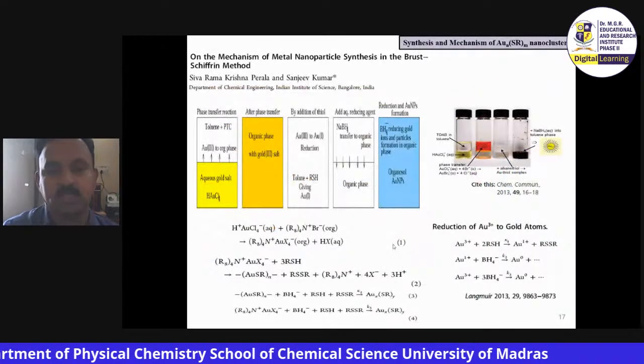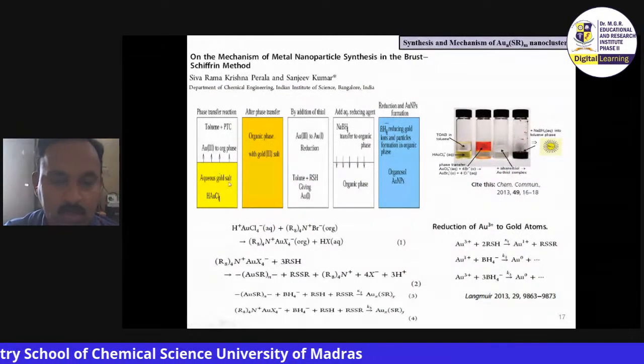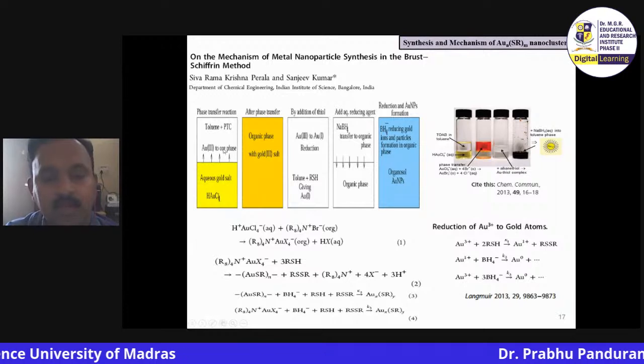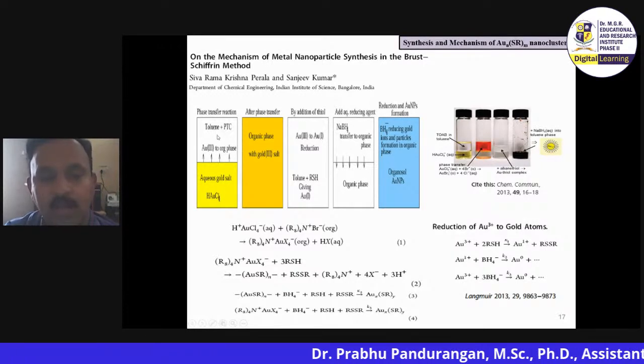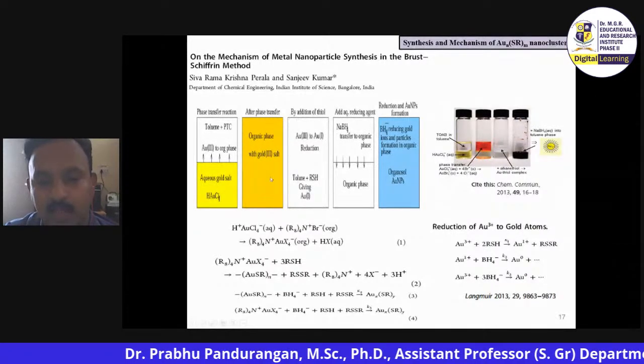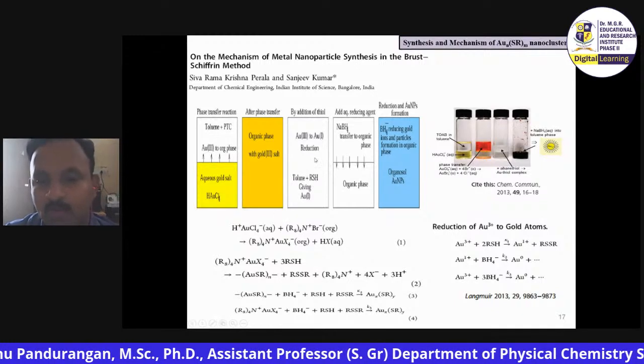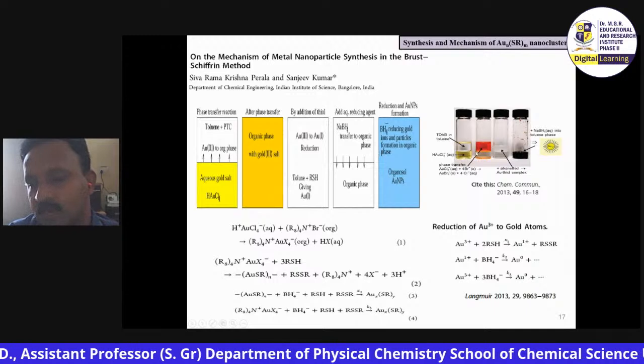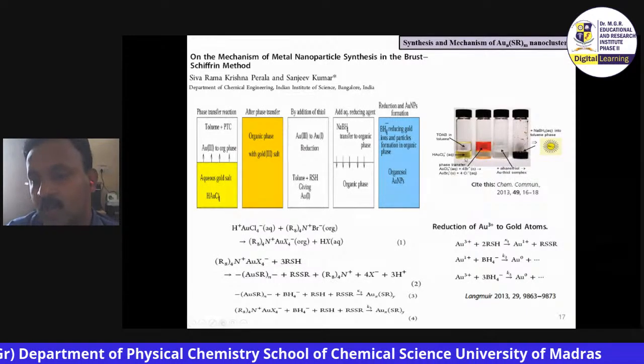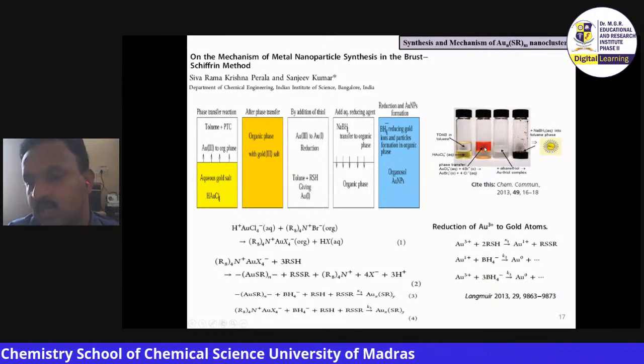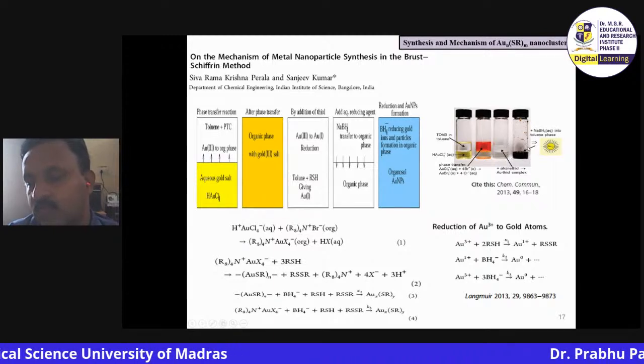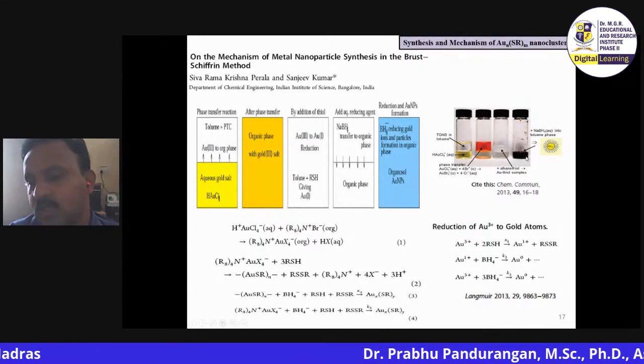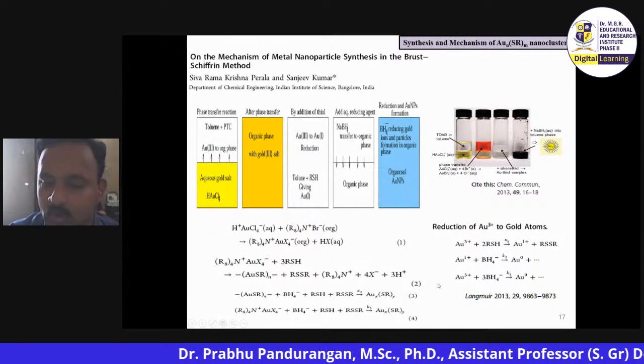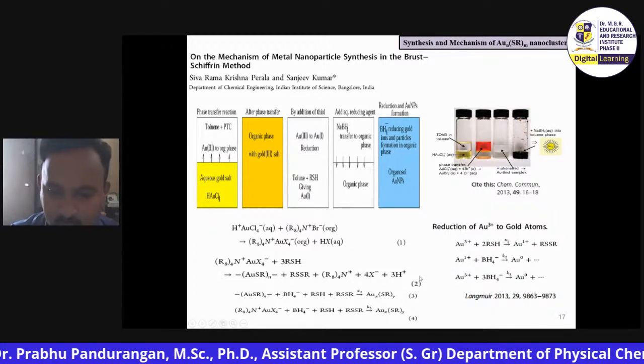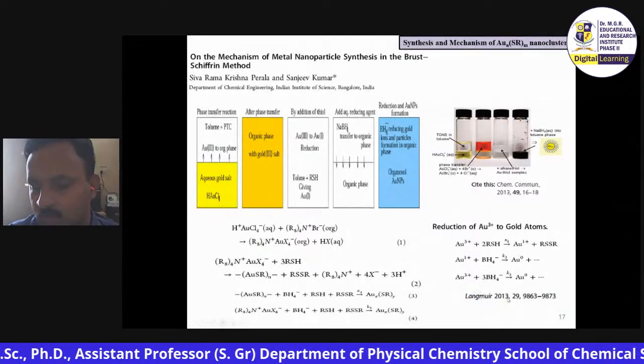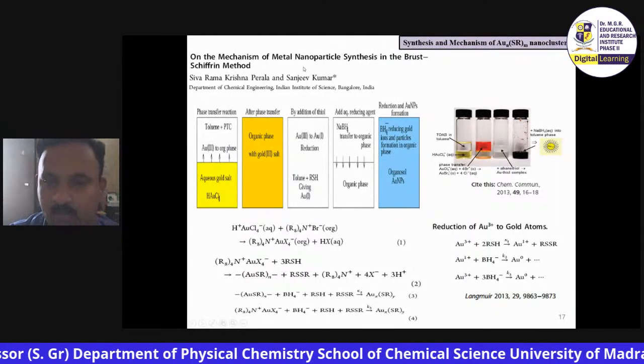So how do we synthesize this nanocluster? I take a gold salt in an aqueous medium, and you can phase transfer this with the help of a PTC into toluene medium. That means organic medium, and you can add thiol to it. The steps form an atom, and the atoms form a particle. You can see the different stages happening to the particle. Initially it is slight yellow in color, then it turns orange, then it turns to a white precipitate, and then it converts to a brown-black precipitate or a solution which has the cluster. These are the mechanisms involved. Given the time, I'm not going into the details. You can find this article in Langmuir 2013 about the mechanism of metal nanoparticle formation.